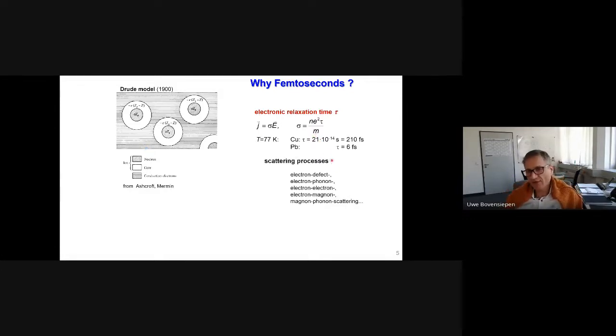We can measure the electrical conductivity. For example, here I show data for 77 Kelvin, and from sigma you find that this electronic relaxation time is several hundred femtoseconds. For lead, this is only a few femtoseconds. So on the femtosecond time scale, scattering processes occur in metals. And the microscopic nature of the scattering process, as I've mentioned, is certainly different. So I list here quite a number of scattering processes between microscopic excitations of several degrees of freedom.